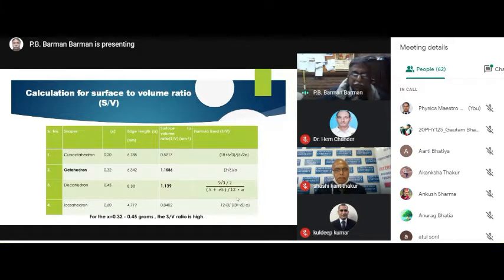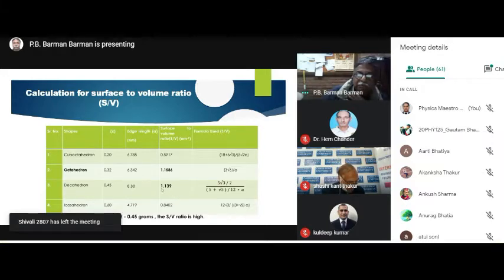We have already seen through these various figures why the octahedron, at the value of PVP at 32%, is more effective. Looking at the octahedron surface, the surface to volume ratio is more, that is 1.186, followed by decahedron at 45% PVP at 1.139. But definitely 32% plays a very important role, because the surface to volume ratio is maximum at this point, so the sensor performance at 32% PVP is maximum.